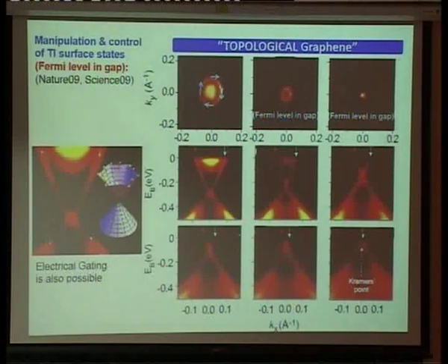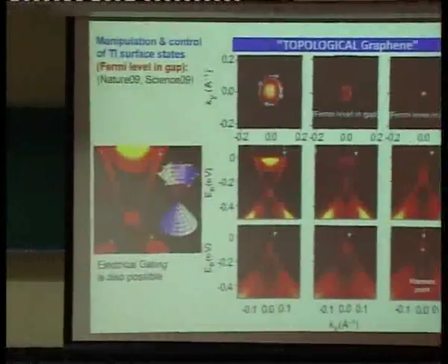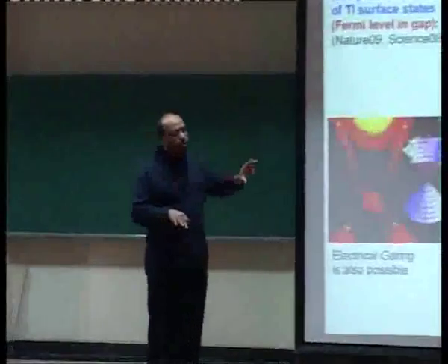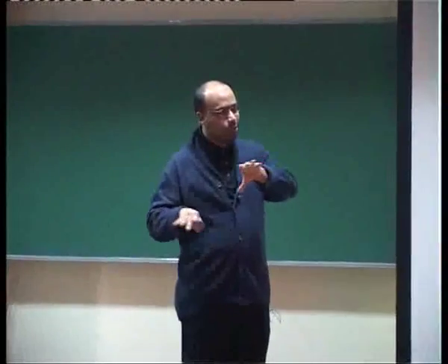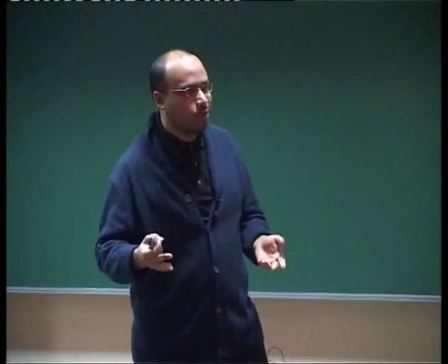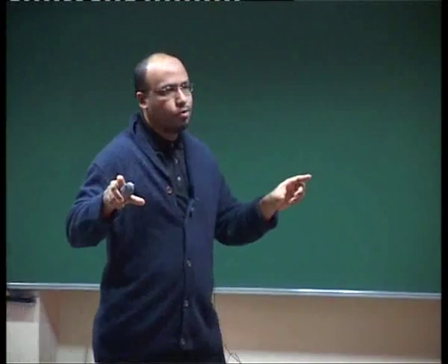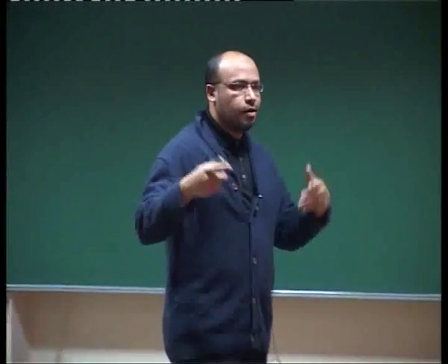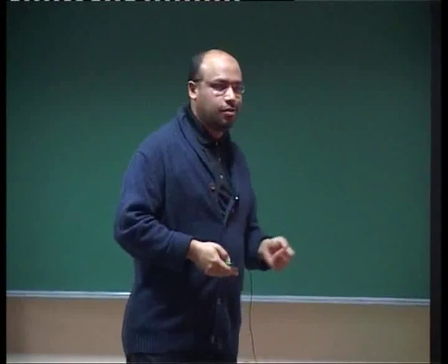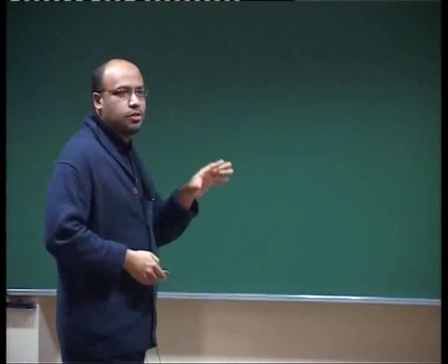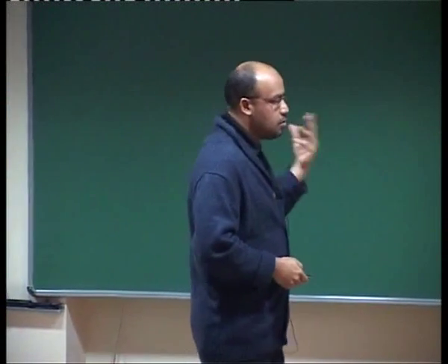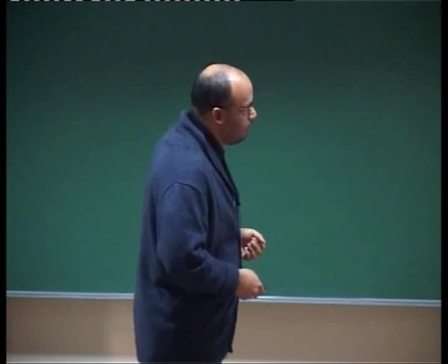If there is a chemical reaction, then the surface states get pushed below the level, but they're still protected as long as your oxide layer is not topological. Then you have an interface, so it's protected because the oxide layer would be trivial, not Z2. So even in that chemistry, there's interesting topological physics to be worked out.